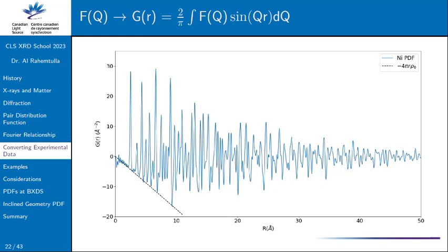I might have one more quick note, because I'm not sure if it was mentioned. The intensity of the peak depends on how many neighbors there are at that distance. It also depends on how strongly those neighbors scatter X-rays, so heavier elements will create stronger peaks. It depends on the scattering power of both elements making up the pair. If you do a nickel oxide, your nickel peak is probably going to be the strongest because nickel scatters a lot more strongly than oxygen.